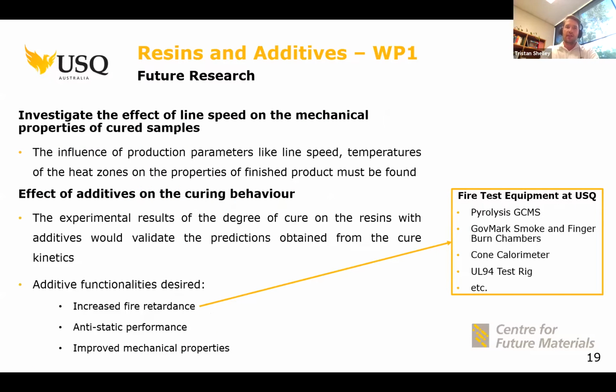And some future activities around work package 1, investigating the effect of the mechanical properties on those increased line speeds, because if you've cured too fast, you may end up with micro cracking within the pultrusion, which may actually lead to a detrimental effect on the mechanical performance of the pultrusion. So investigating all of the effects of the curing process, and also looking at increased functionality of the pultruded product through the addition of additives.